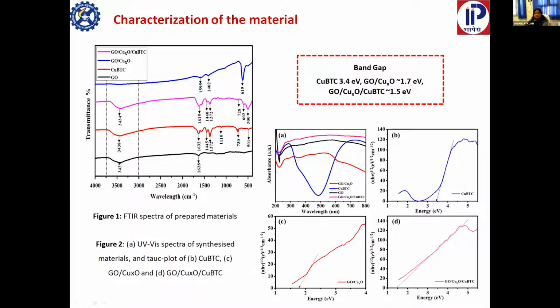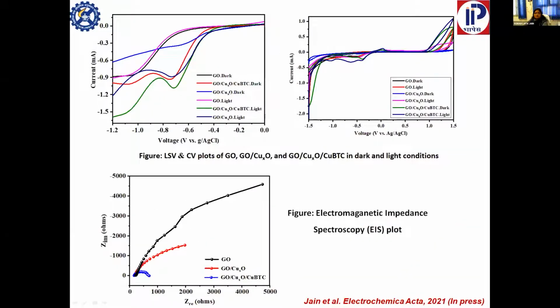This is the characterization. If we look at the band gap values by using the UV, by the Tauc plots, we determined the band gap values, and our hybrid system showed the lowest band gap compared to its constituent components, showing its higher visible light activity. Similarly, if we look at the photoelectrochemical properties, we can see that our ternary hybrid material is showing the higher current density. It is also showing less electron hole pair recombination, meaning the hybrid material is much more efficient for the reaction than its other compositions as well as the constituent components.